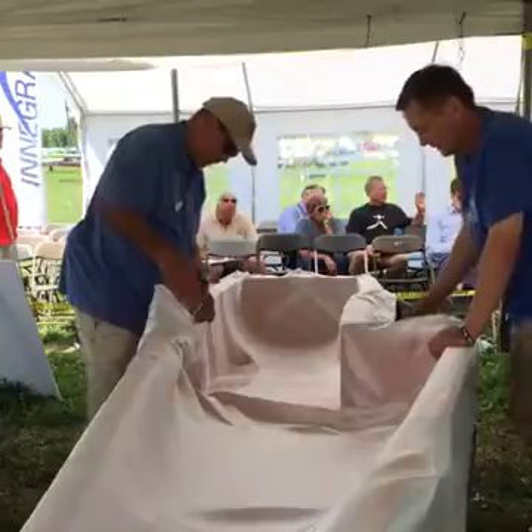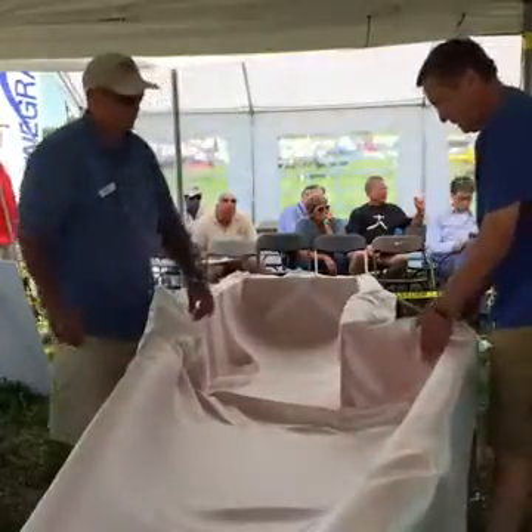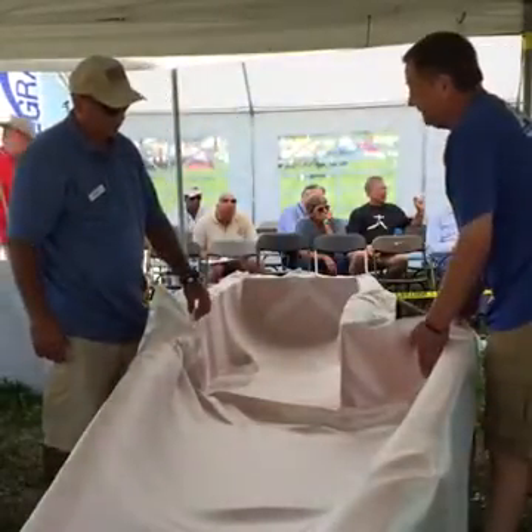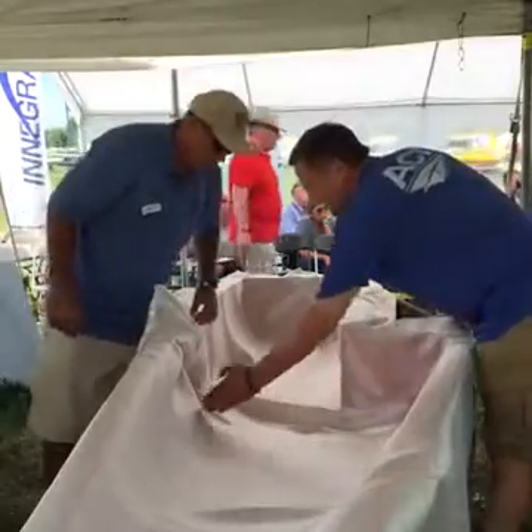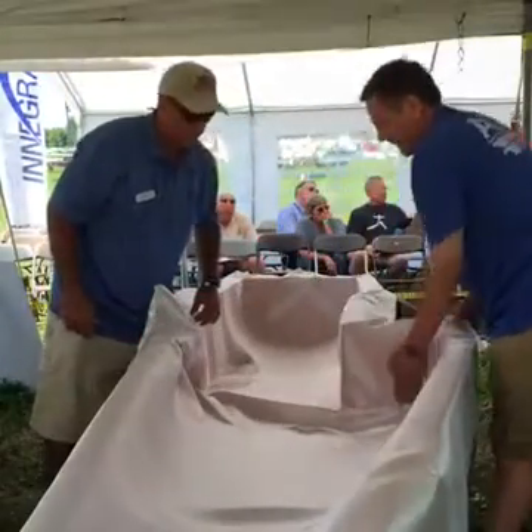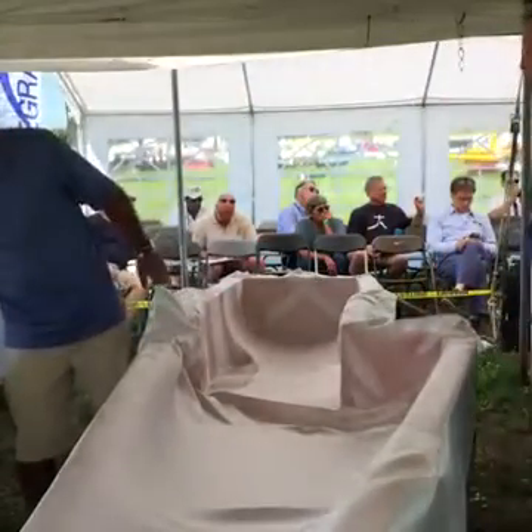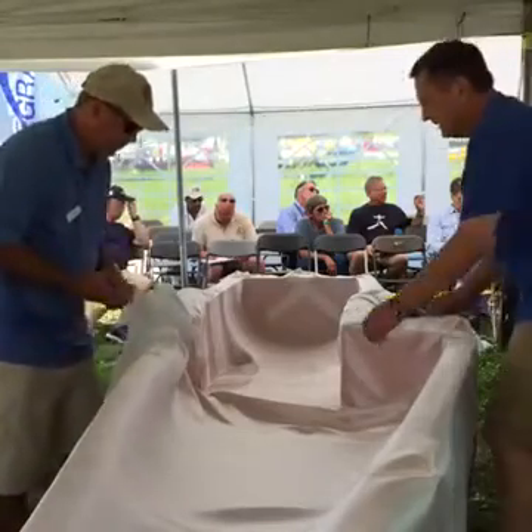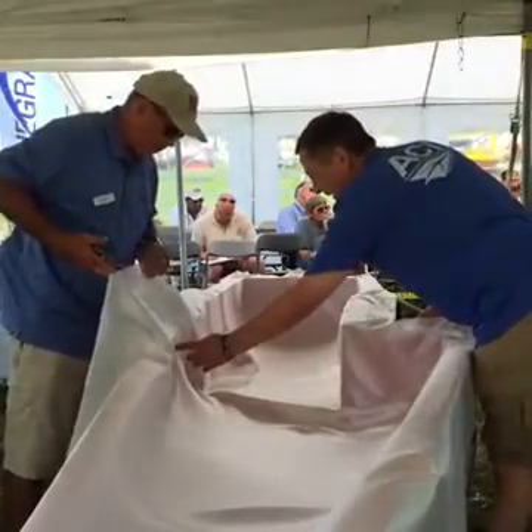So we have 3 passes of 10 mils thick gel coat that goes down first. In between each layer, you let it go off just slightly. Put your second layer behind it, let it tack. Put your third layer down, let it tack.